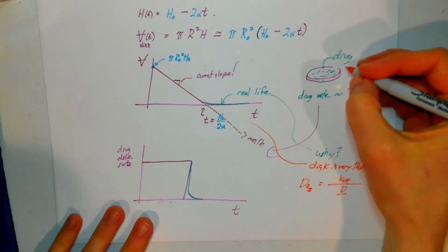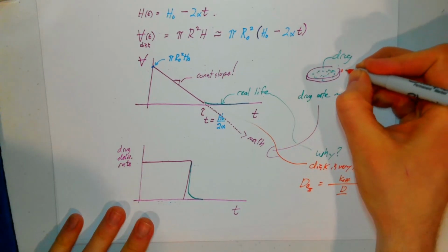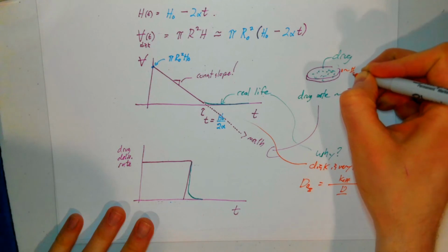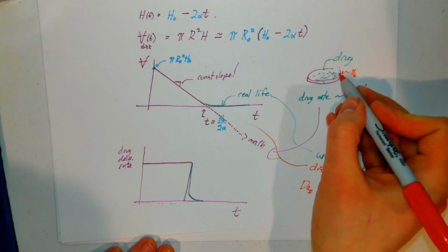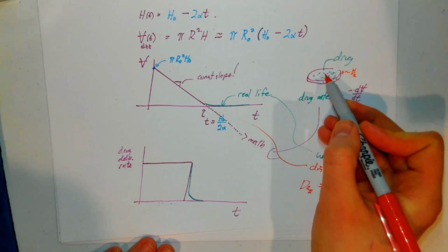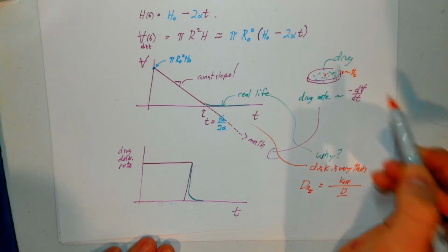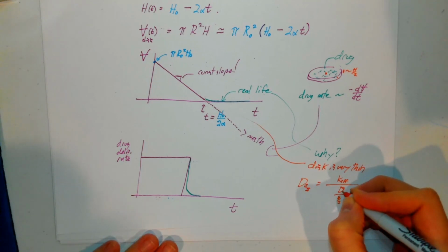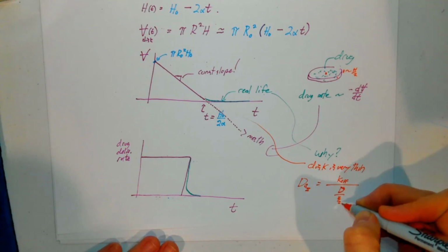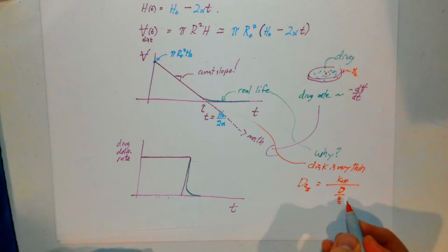And in particular, for this, the appropriate length scale would essentially be h over 2 for a disk. The length scale is from the surface to the center of the device, and that shortest distance is basically the half thickness of that disk. So the second Damköhler number is k effective over the diffusivity times h over 2 squared. And basically, what does this mean?